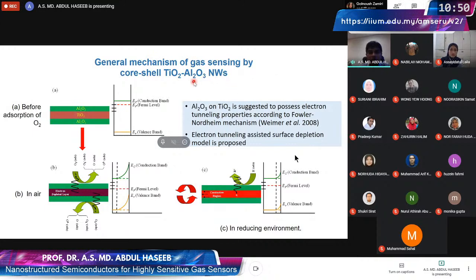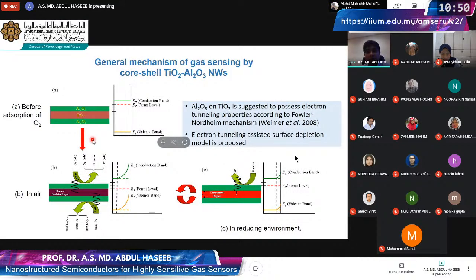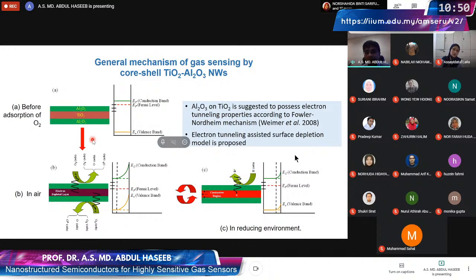And when we mix them together, what we see is that aluminum oxide is forming a continuous layer at the top surface. And we were initially puzzled why, in spite of this insulator, we still get the signal from this. So we looked into the literature and we found out that there is a mechanism that has been suggested already by Fowler and Nordheim. They have shown that when aluminum oxide is present on a conductor at a very small thickness, lower than 40 nanometer, then this layer can allow electron tunneling. And we believe the same mechanism is happening here.